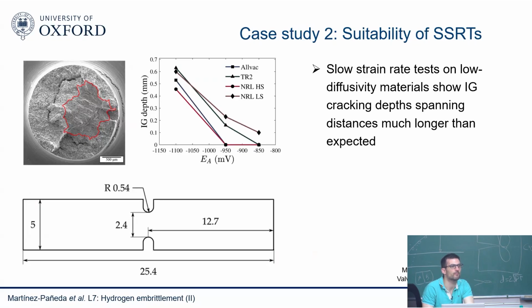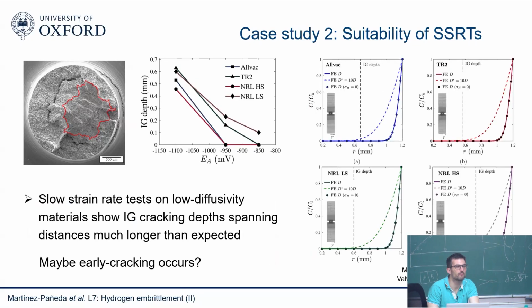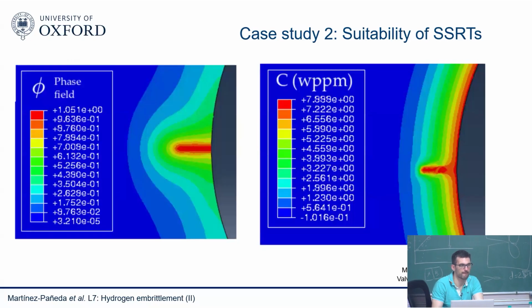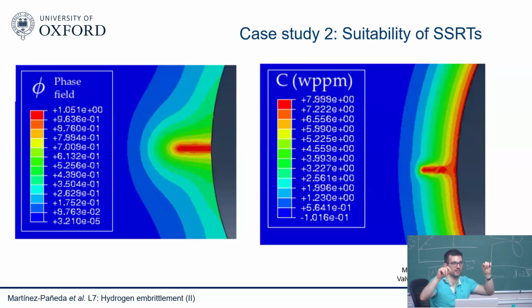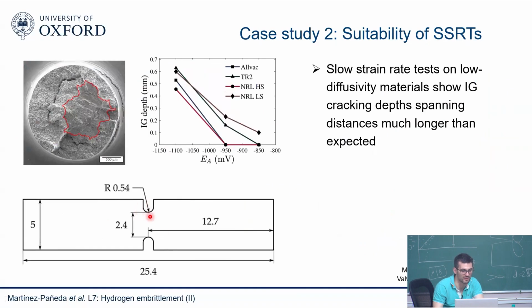If you go to your actual results, the next slide, what is the domain size relative to the experimental sample? Is it very near to the crack tip that you're modeling? Well, we model the entire sample. I don't remember. This figure is just meant to show that, but we model the entire sample, and maybe we can figure it out from the notch size. You can see more or less the curvature. So I'm plotting, zooming in somewhere here.